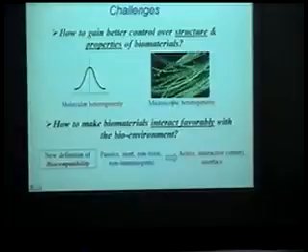These are the two things I identify, of course. First of all, how do we make biomaterials with well-defined structures and functions? Right now, we're not really very good at doing that. For example, if you're making a polymer using traditional chemical synthesis, this is what you'll get in terms of the size of the product. I call this molecular heterogeneity, which is essentially a Gaussian distribution of different chain lengths. The number of species involved can be huge, like hundreds of thousands or millions. So you think you're making one polymer, like polyethylene, but actually you're dealing with many, many different kinds of polymers, each with a very distinct structure and property. Of course, that's going to influence any biological applications.